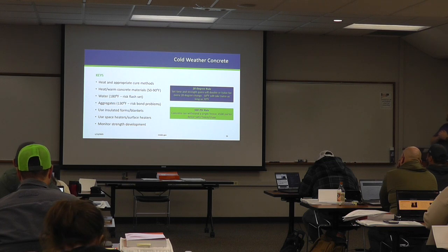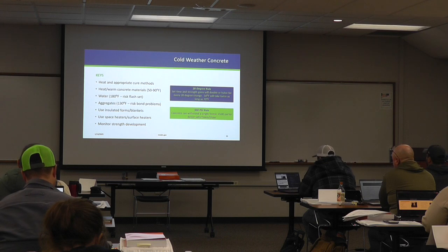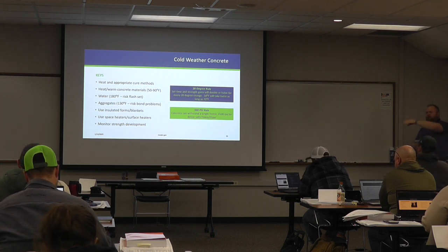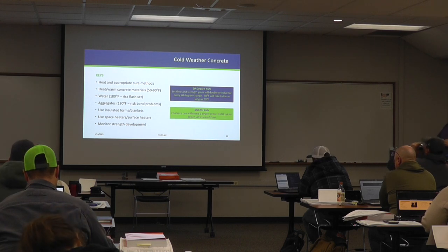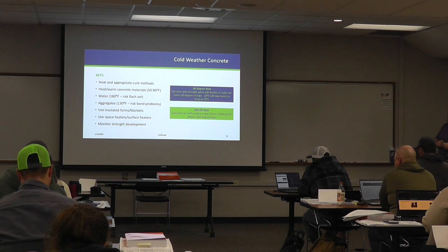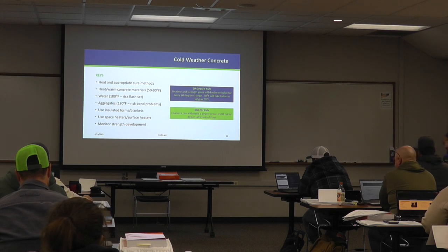Now some keys to keep in mind for cold weather concrete. We want heat and to use appropriate cure methods. We're going to heat or warm our concrete materials so that the concrete shows up at 50 to 90 degrees, whether it's middle of summer or middle of winter. That concrete's fresh properties need to be within 50 to 90 degrees while it's being placed. If we're using hot water, we don't want that water to be above 180 degrees at the plant because then we could risk flash set of our concrete.